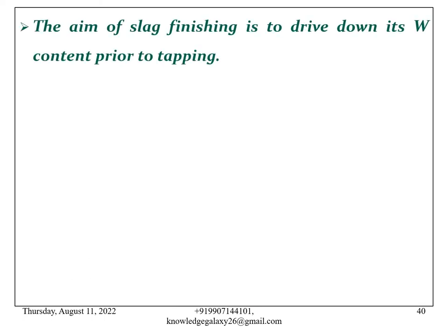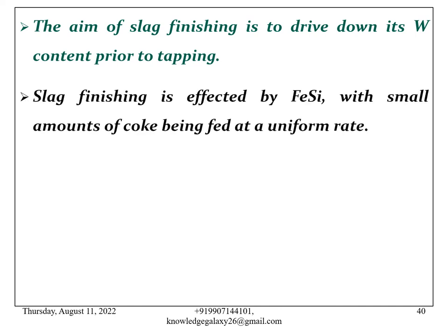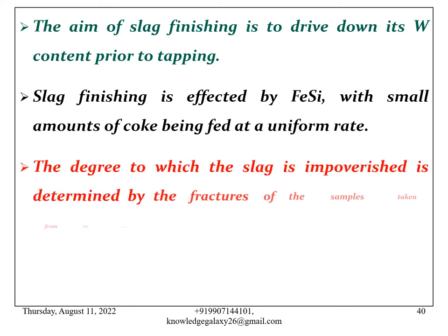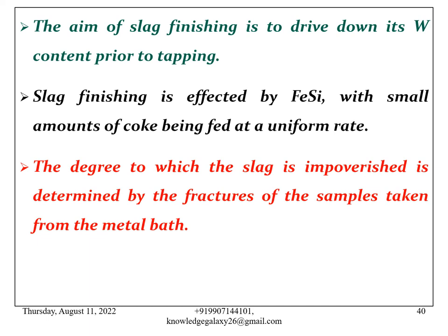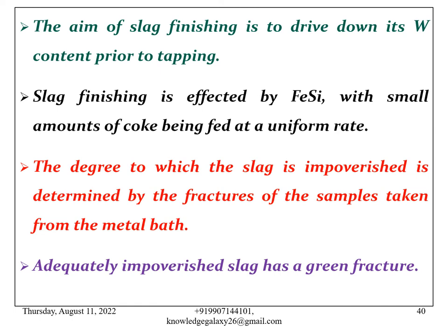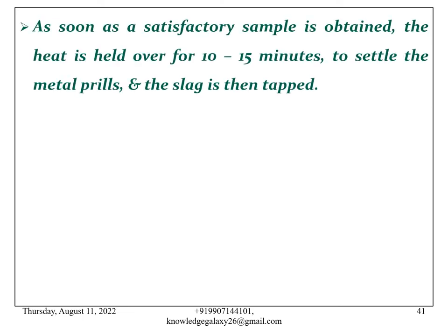The aim of slag finishing is to drive down its tungsten content prior to tapping. Slag finishing is effected by ferrosilicon with small amounts of coke being fed at a uniform rate. The degree to which the slag is impoverished is determined by the fractures of the samples taken from the metal bath. Adequately impoverished slag has a green fracture. As soon as a satisfactory sample is obtained, the heat is held over for 10 to 15 minutes to settle the metal prills and the slag is then tapped.